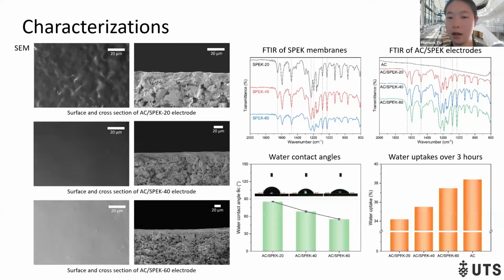The characterizations confirm the successful fabrication and physical properties of the AC/SPEK electrode. The SEM image shows the surface and cross-section morphology of the electrodes. As the sulfonation degree increases, the coating appears more compact and uniform. For the water contact angle, we can see that as the sulfonation degree increased, the contact angle decreased, suggesting enhanced surface hydrophilicity, which may benefit the ion transport. Additionally, the water uptake test shows increased water absorption with larger sulfonation as well.